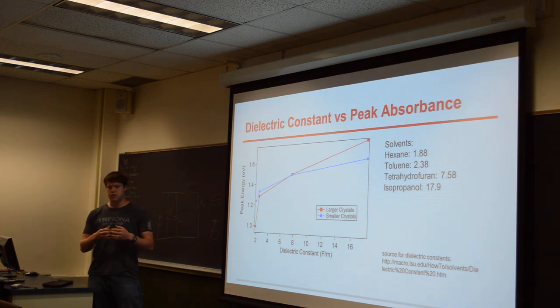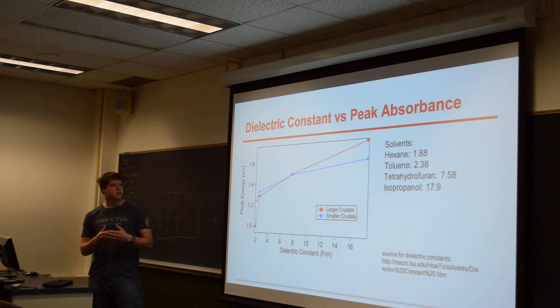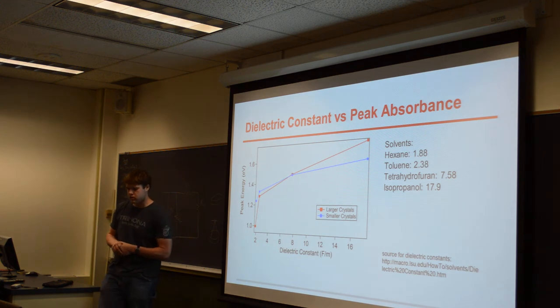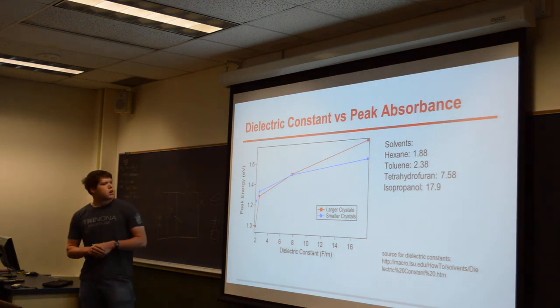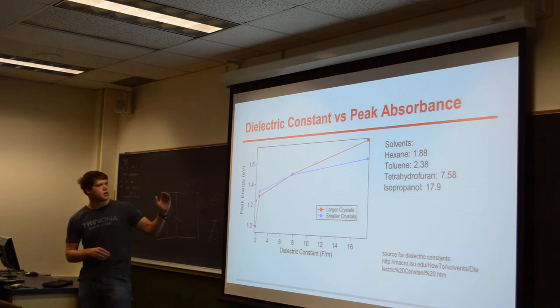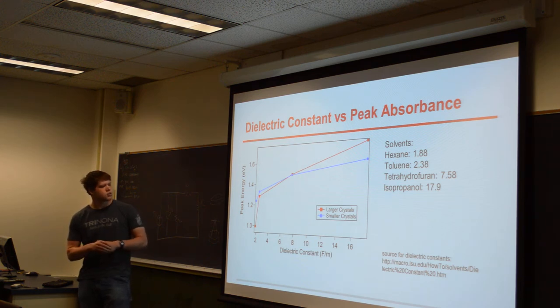This pretty well confirms that this is a plasma effect that we're seeing. The plasma effect is effectively an electric wave on the surface of the material, so changing the dielectric environment alters how the wave propagates across the material, which is why we would expect to see a trend like this. This is also somewhat interesting as we would hope to be able to increase this peak energy to be able to use it in a solar cell. We can see that it does increase, but it also levels off, so it's not clear through methods like this how much we could really increase that peak energy.